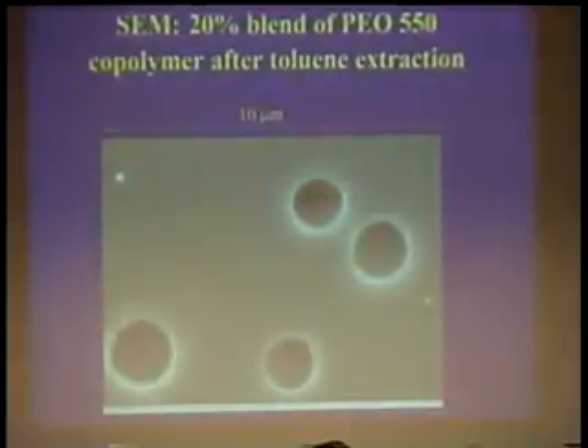Here's something that would be totally unexpected to give you information along those lines. It's a scanning EM of the surface of a 20% blend of PEO550 copolymer after it's been extracted with toluene. Now, what's the significance of toluene extraction? That is that the copolymer is soluble in toluene and the matrix is not. So the idea here was to try to get a handle on the location of the copolymer in the blend.